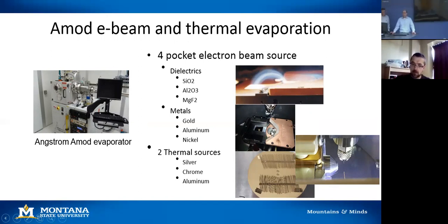In this case, with the electron beam, you can get high enough temperatures, you can actually melt silicon dioxide. We don't melt it, we sublimate it, but you can evaporate silicon dioxide, aluminum oxide, magnesium fluoride quite easily. We also have two thermal sources in the tool, mostly for metals. For different reasons, you'd want to use this source.